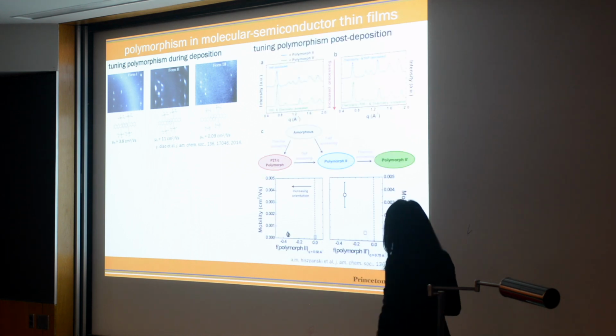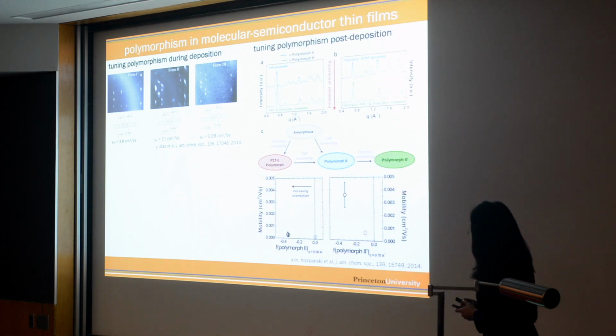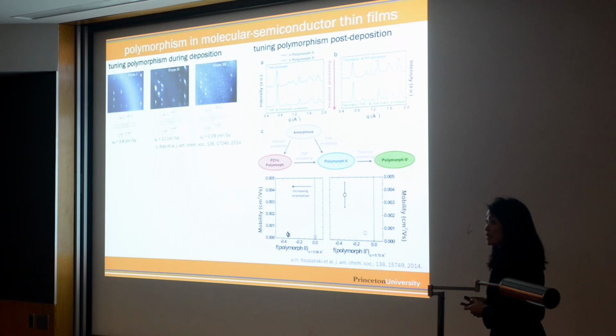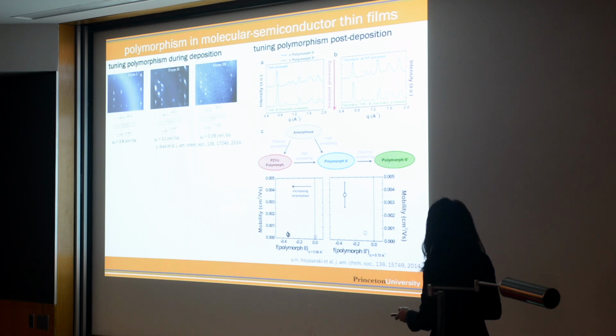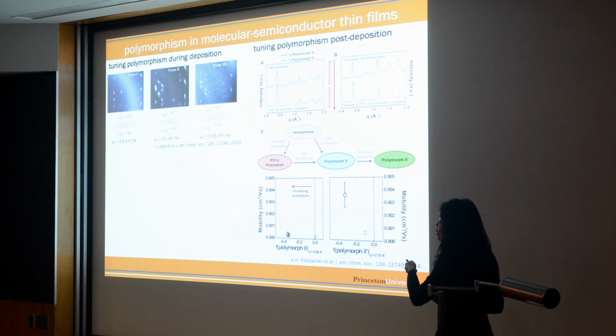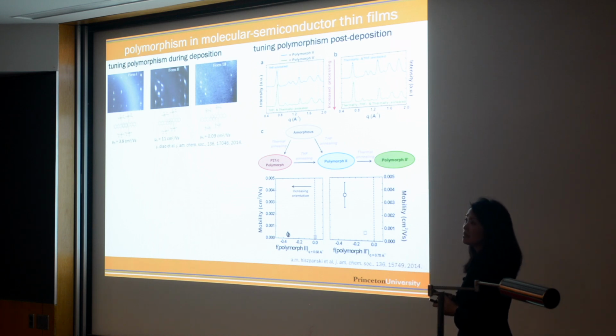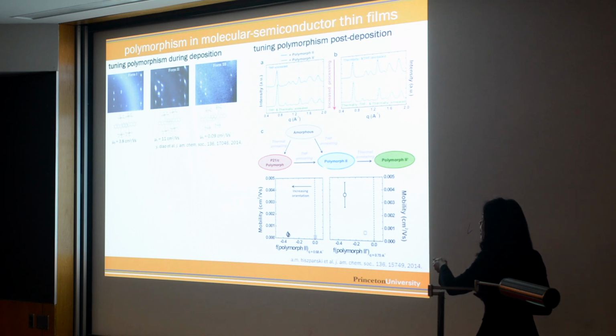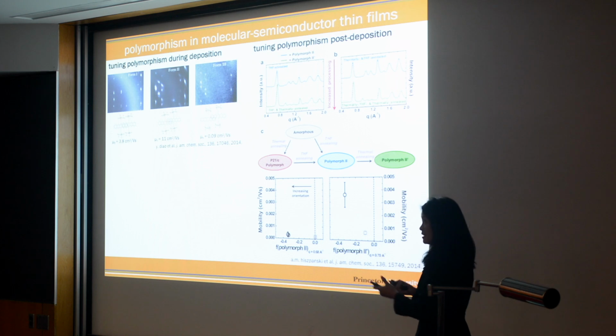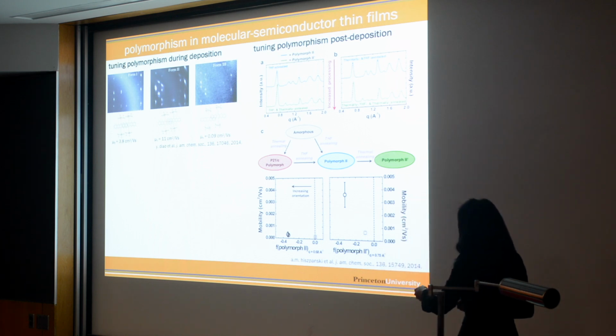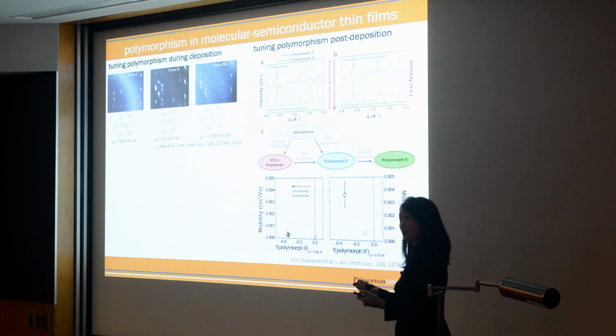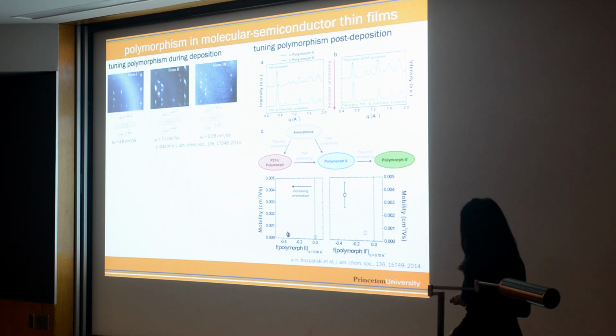In the same issue of JACS, we also published a polymorphic story. Here, this is with contorted hexabenzocoronene. And here, what we showed is that depending on how you post-deposition process the amorphous film, you can access two different polymorphs. This is the crystal structure and the X-ray diffraction data that we collected here at CHESS. And what you can see is the mobility is a strong function of not only the polymorph, but also the orientation. And we can separate these two contributions by doing systematic transistor measurements.